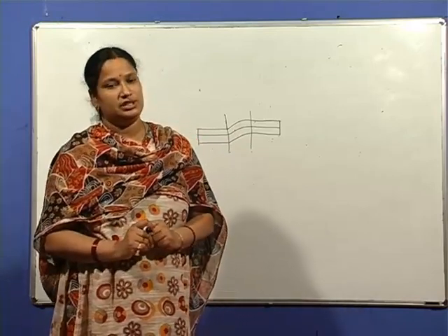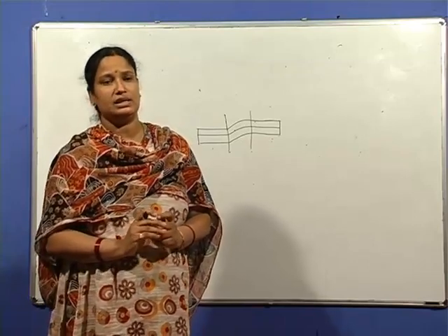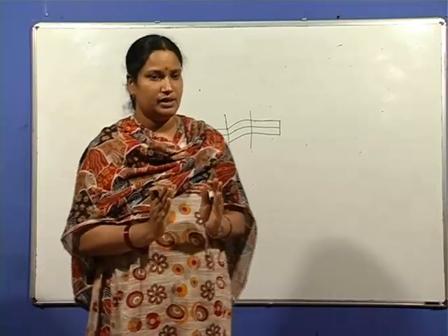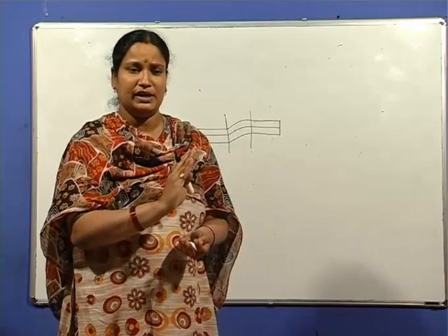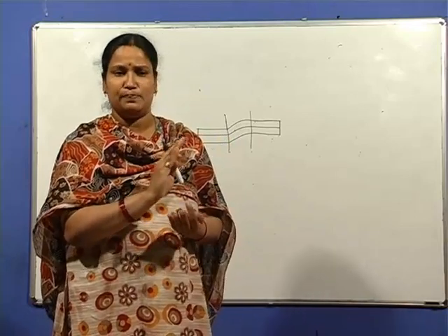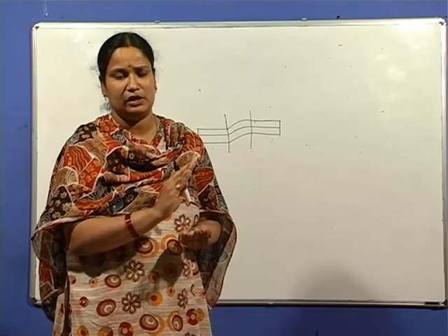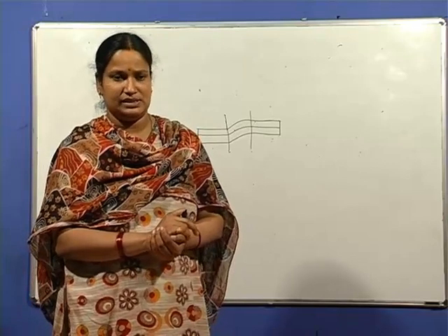So this is about the kink bands, mainly seen in the case of HCP metals when they are loaded in compression, and that too when the applied stress is perpendicular to the main principal slip plane, that is the basal plane, commonly the basal plane of the HCP metals. So this type of kink band is seen.